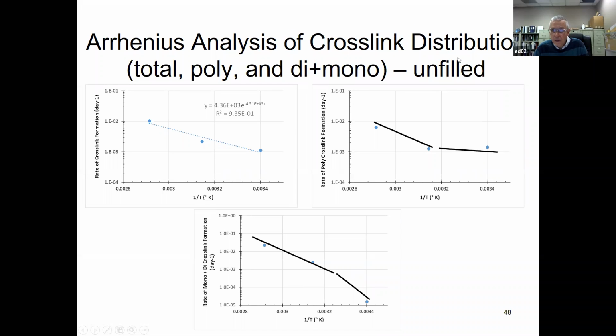And then here is our unfilled compound: total crosslink density, polysulfidic crosslink formation, mono and disulfidic crosslink formation, plotted Arrhenius style. For the total, we see no evidence for non-Arrhenius behavior or mechanism change, but we see that in the polysulfidic, and we see it in the mono-disulfidic crosslink type measurement, where there's a change in mechanism around 50 degrees centigrade.